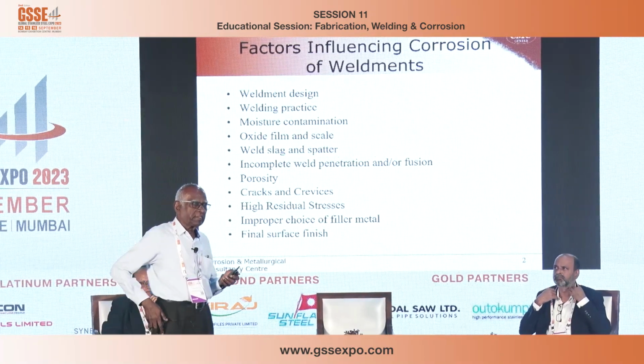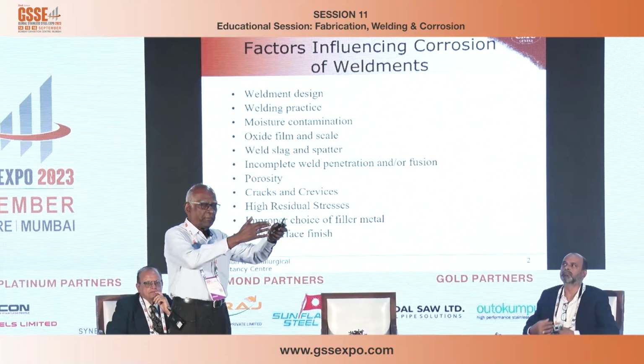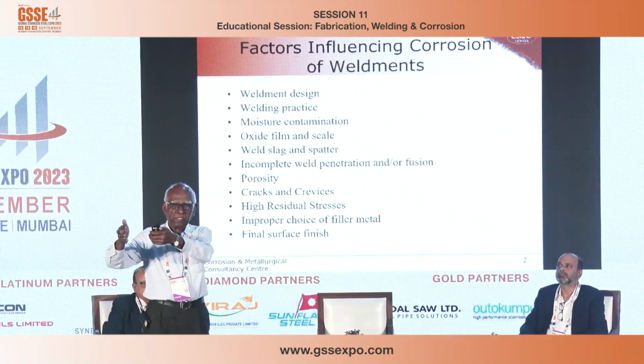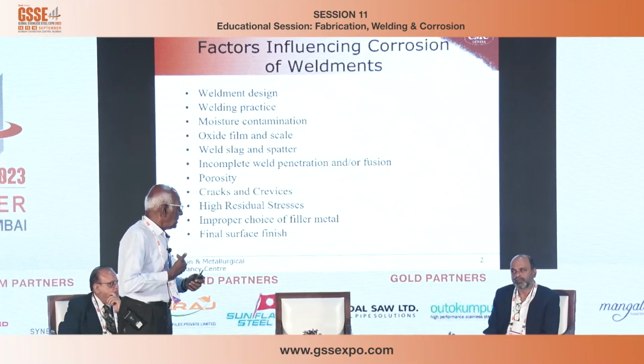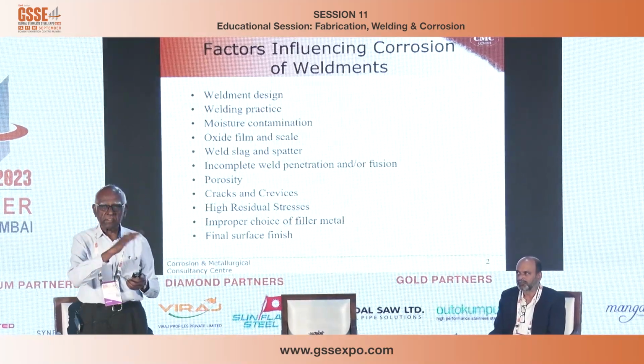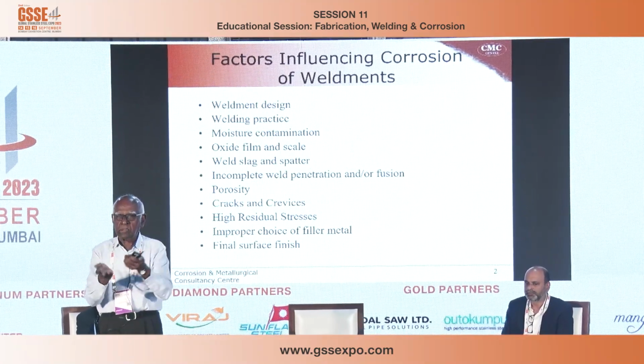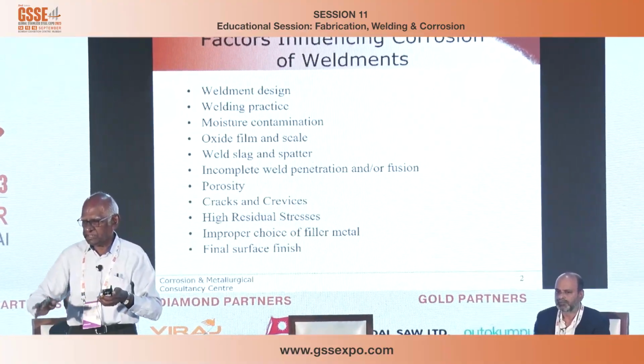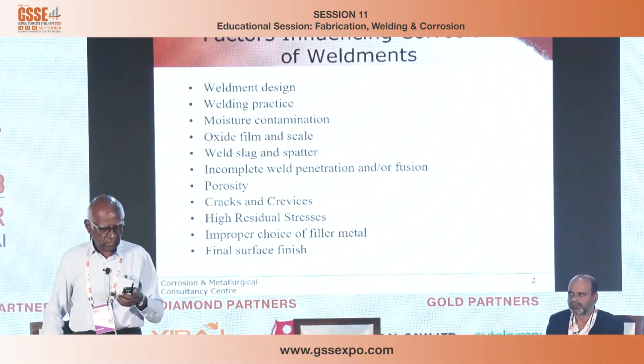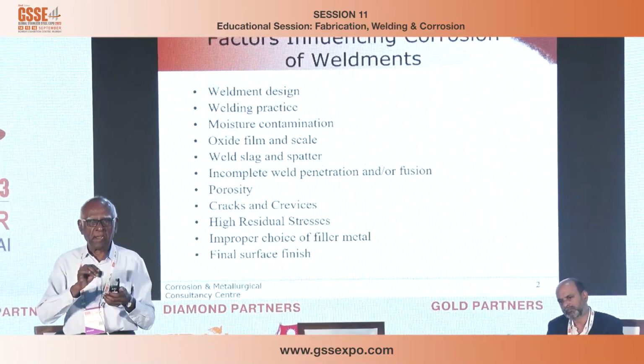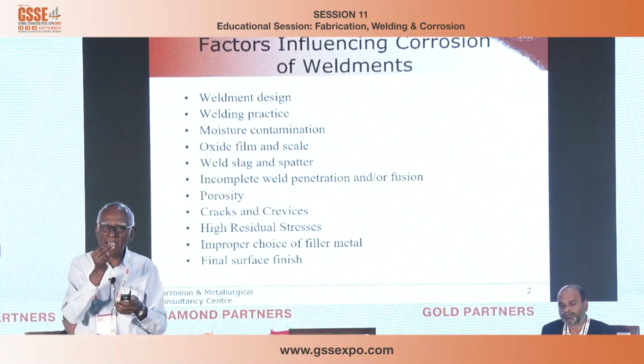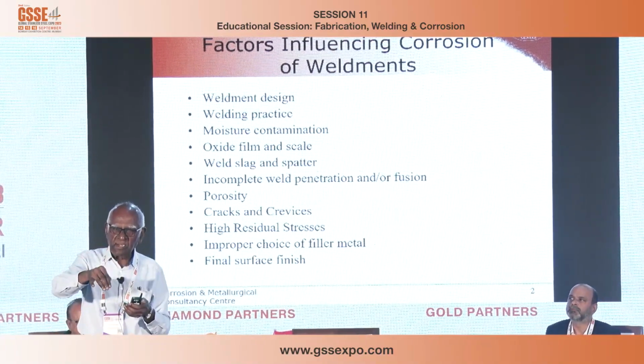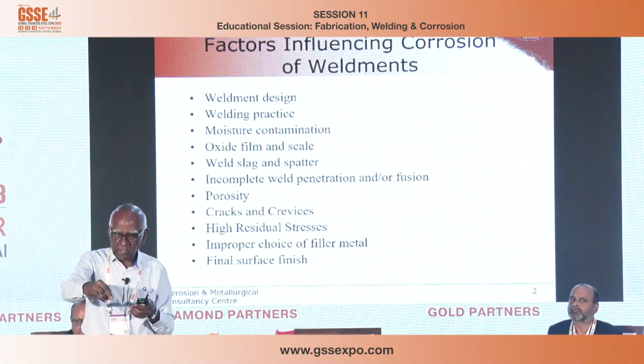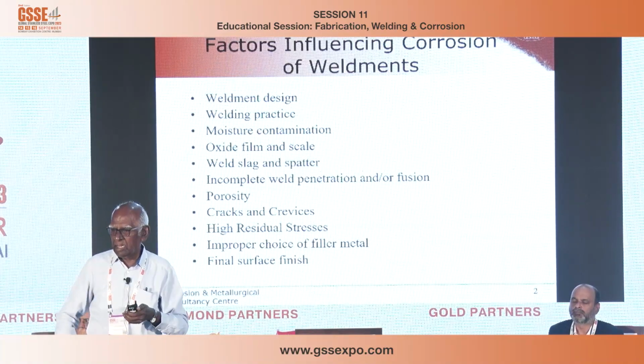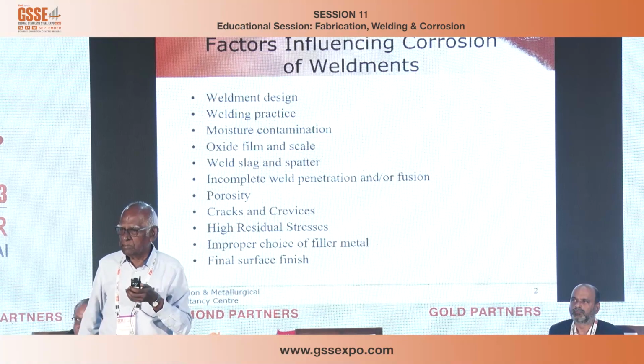Very big companies have a separate workshop for carbon steel and a separate workshop for stainless steel. Am I correct? Yeah. So you don't mix stainless steel welding with carbon steel welding. You should not mix. As soon as hot slag and spatter comes and sits on a stainless steel surface, that particular location is no more stainless steel. And you'll get into a corrosion problem there.